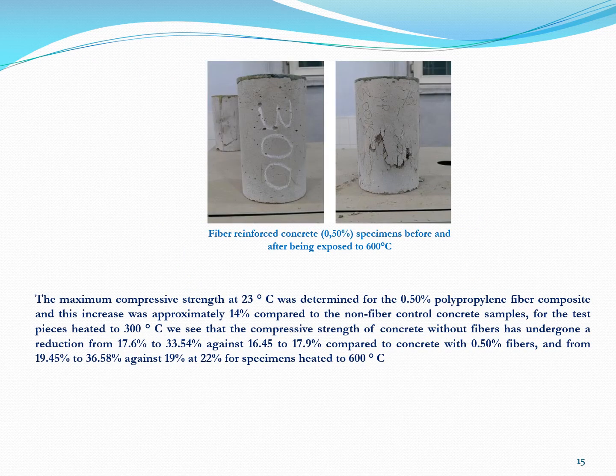Here we show the fiber-reinforced concrete specimens before and after being exposed to 600 degrees Celsius, for the range of 0.50% fibers in the concrete. The maximum composite strength at 23 degrees Celsius was determined for the 0.50% polypropylene fiber composite, and this increase was approximately 14% compared to the non-fiber control concrete samples for all ranges of temperatures.